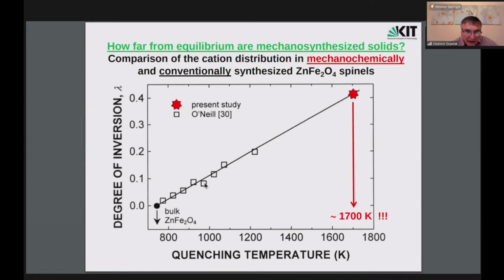These squares are not our data. They are data for conventional mineral zinc ferrite. I think the mineralogical name is franklinite, and O'Neill measured, I think using neutron diffraction, the temperature dependence of cation distribution in this material between tetra and octa sites. And you see that with quenching temperature, it was efficient to quench the material, freezing the degree of inversion up to 1200 K. And we extrapolated this data with a line, because it was only imagination how far from equilibrium we are.